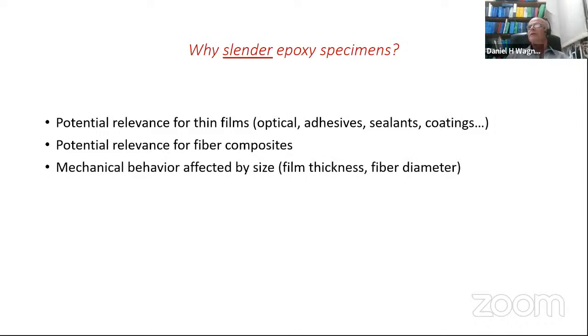The reason we are interested in slender specimens in general is that the mechanical behavior depends very much on the size of the specimens. Film thickness and fiber diameter are key parameters when measuring mechanical property. And also because it's difficult to make. And this is something I wanted to do for many years, to find the right student which is obstinate enough to be able to address this challenge of preparing very thin fibers and films of epoxy.